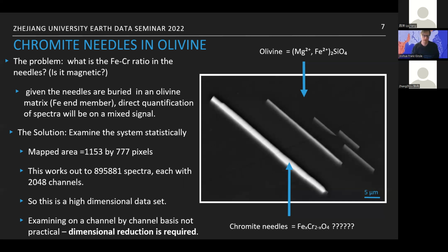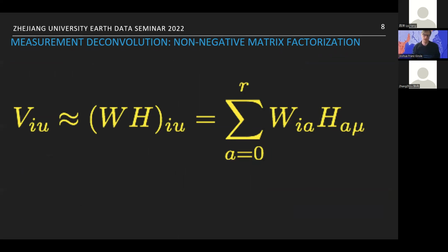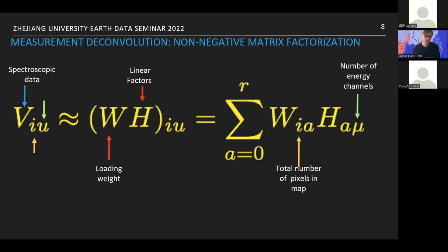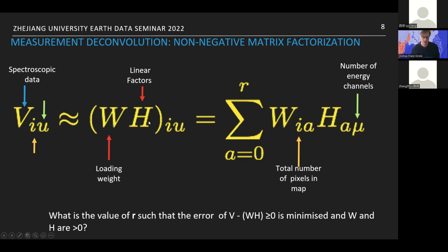So the first thing is again, this is your standard equation describing how deconvolution works. This is a slide mainly meant for the more physicists in the audience because they need equations. And the key bit here is that the spectroscopic data, any one spectrum, is thought of as a linear combination of both a loading weight and a linear factor. And this factor here is some spectral shape. And if we deconvolve it such that we also apply a non-negativity constraint, this gives us non-negative matrix factorization.